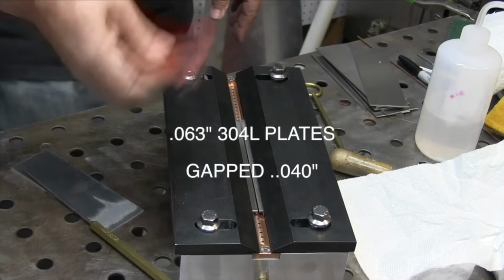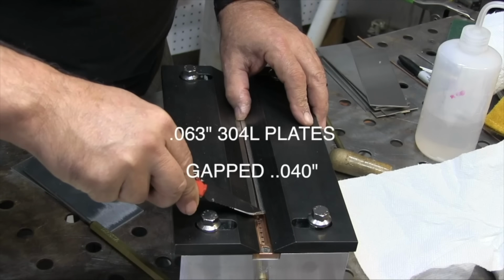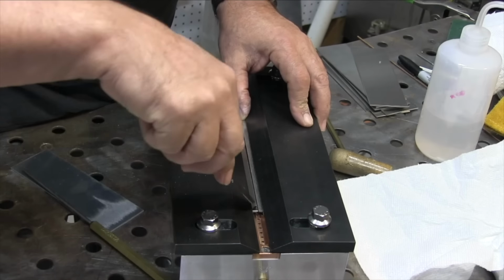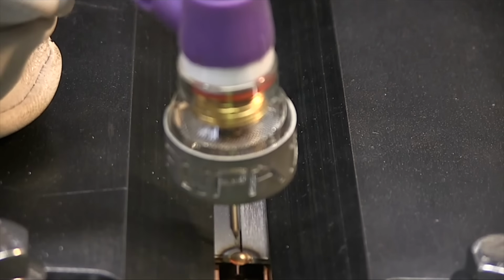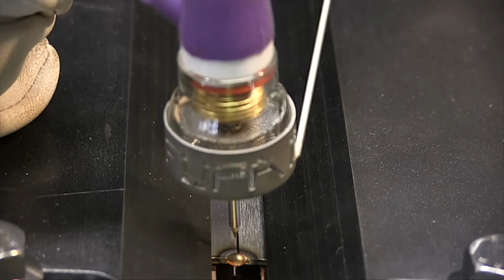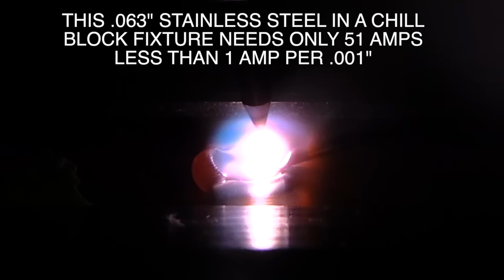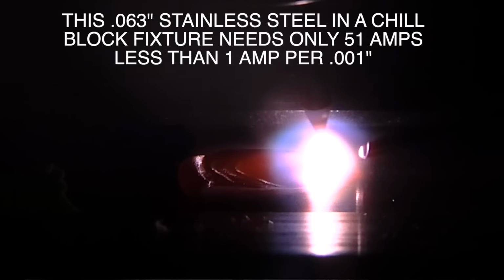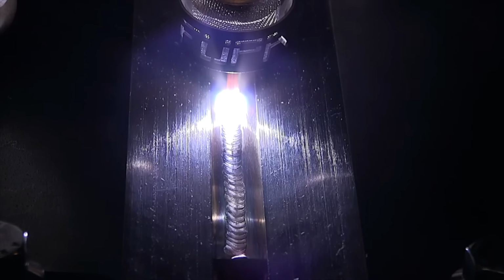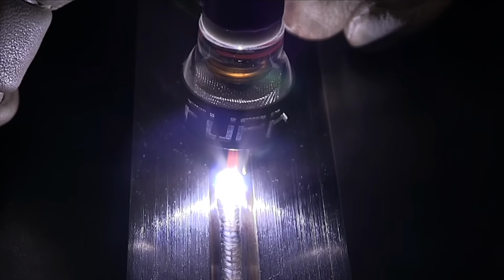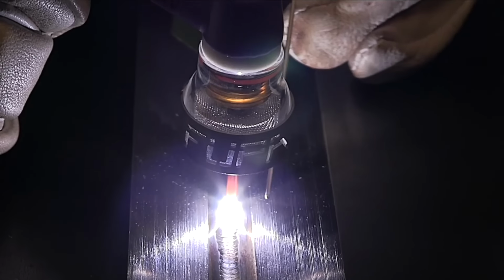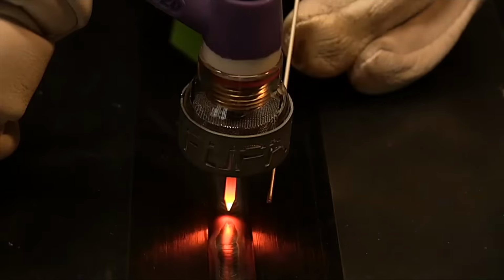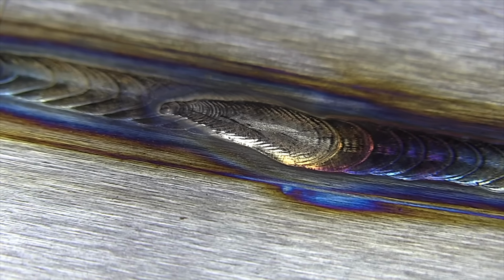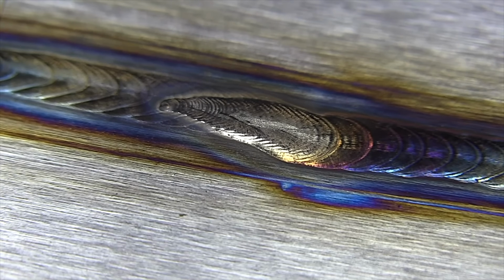Well, now let's take a look at a similar joint, a little bit thicker in stainless steel. This is 063 304L stainless. I'm just going to weld part of it here. Now remember, the carbon steel took more than 1 amp per thousandths of a thickness to get good, even penetration. This is 063, only required 51 amps, and that was plenty hot. Even with the chill block fixture, it required less than 1 amp per thousandths of an inch to get the job done here. Just an example of how stainless steel requires less amperage than carbon steel, typically.